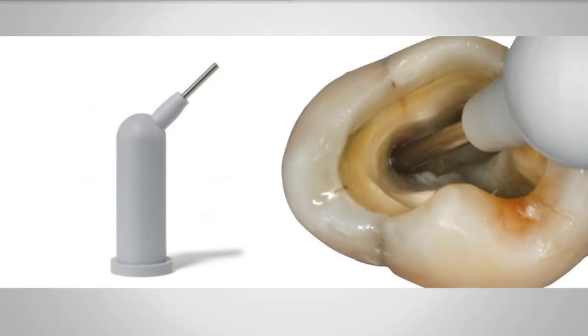Typically, if we're trying to pack down into a root canal, it can be really tricky to manipulate the composite material right down on top of the root filling, knowing that we've only just placed 2 millimeters and no more. So I think one of the reasons why composite in root fill teeth developed a bit of a bad name is that dentists were not layering correctly, because it was very difficult to adapt the composite at the depths of the root canal, and building up in not 2 millimeter layers but 3 or even 4 millimeter layers with conventional composite, and therefore the composite wasn't actually curing sufficiently well. And that was leading to premature failures, of course.